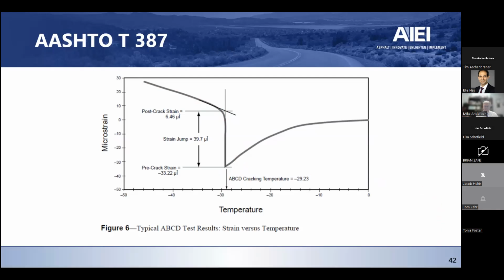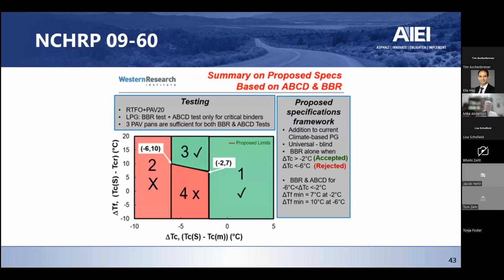It's that critical cracking temperature that we use with the TCS that we get from the bending beam rheometer in order to calculate this delta TF. So the way this is right now, courtesy of the 9-60 folks and Western Research, anything in this region, which is -2 and higher, this is region 1, everything's okay. Anything in this region, region 2, which is -6 and lower, is going to fail. In between -2 and -6, there is a minimum delta TF required, and that changes. It's not just a single minimum, it's across the board, but it gets a little bit more harsh, if you will, as you get lower and lower on that delta TF criteria, such that if you're above that in the 3 region, you pass, below that in the 4 region, you fail. Okay.